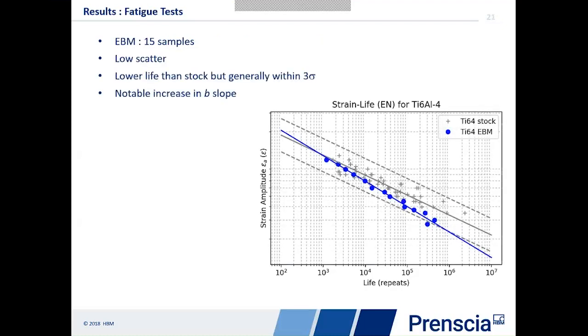So first of all, let's have a look at the electron beam melting. So far, we've tested 15 samples. We've actually tested quite a few more than that now. But the 15 I'm putting here have all been tested with a HIP post-treatment with them. And the first thing we notice is that they've got a very low scatter. They hug the curve very nicely. And that's a very good indication of the quality of the material.